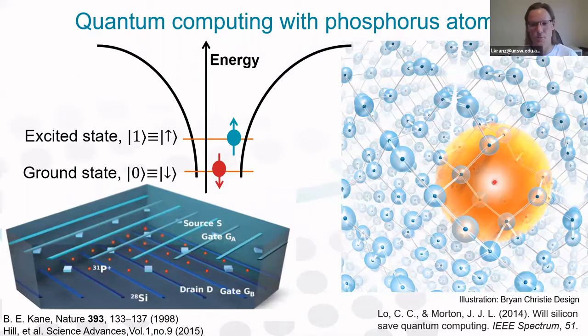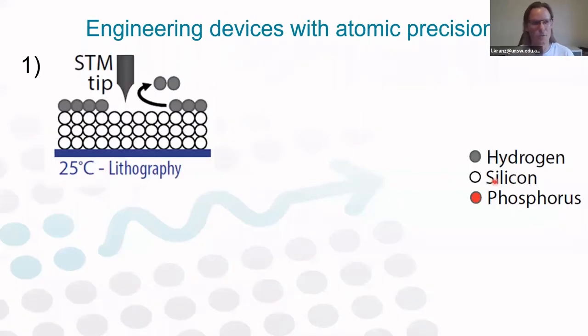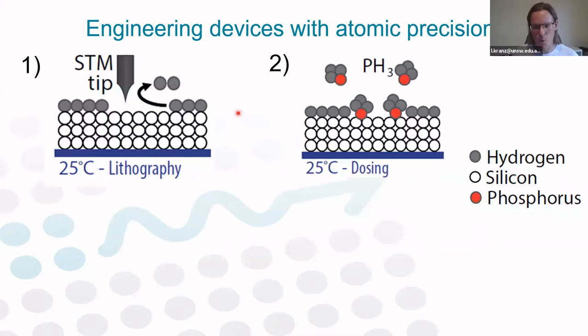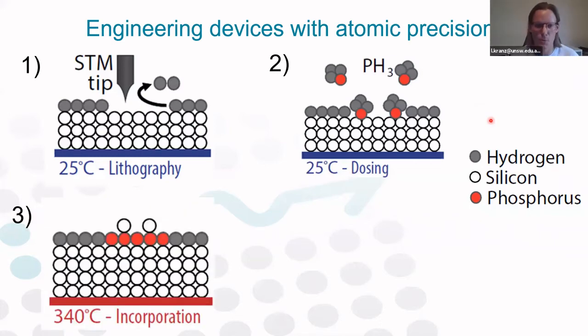So let me briefly explain how we fabricate our devices. So we start with a bare silicon chip with a monolayer of hydrogen on top, and then we approach with the tip of a scanning tunneling microscope, and by applying voltage, we can write any desired pattern into this lithographic mask. We then expose the sample to phosphine gas. Phosphine is PH3, and the phosphorus P is represented with red here. And these molecules will react with the exposed surface of silicon. We then heat up the sample to incorporate phosphorus atoms into the silicon crystal lattice.